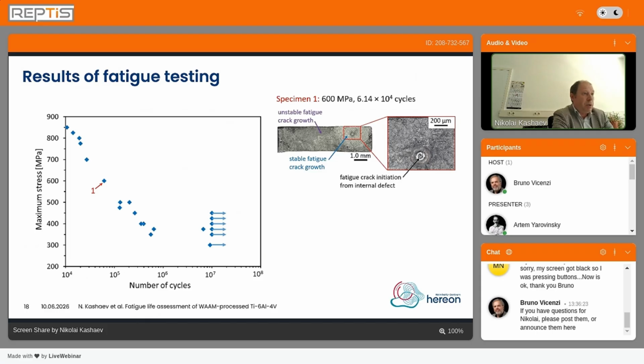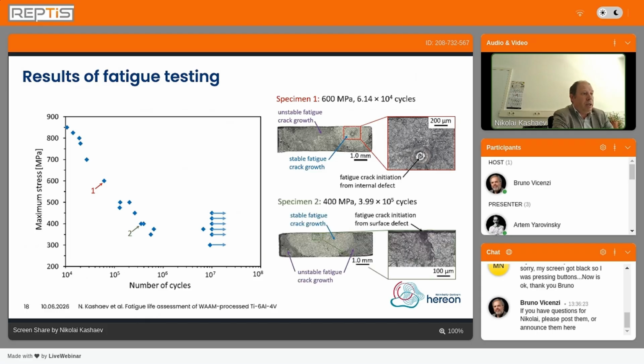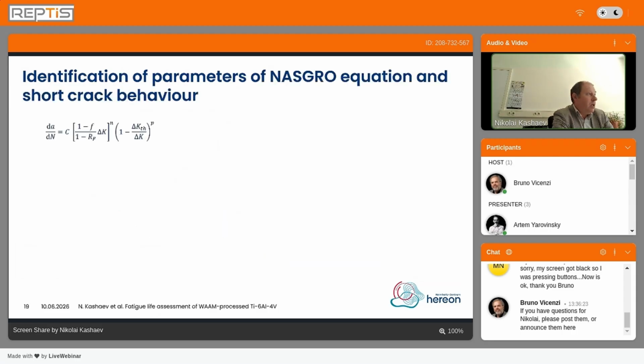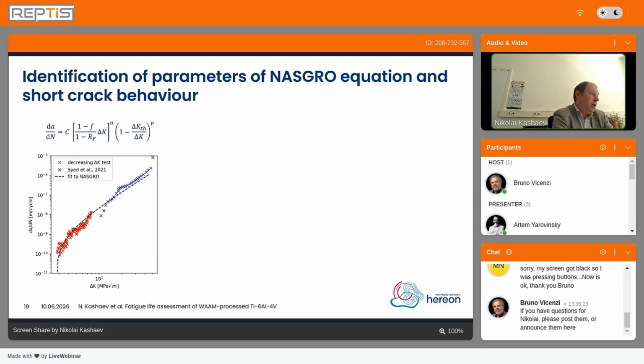The number one marks the typical issue where we have cracks, but we have also another situation if the defect is located directly at the surface. Therefore, we have to extend our model also to consider the possible crack initiation from the surface. And we followed the same approach with the NASGRO equation where we identified the fatigue crack growth behavior and fitted the coefficients of the NASGRO equation. And here we also considered the two possible cases if the crack propagates from internal defects and from surface defects.